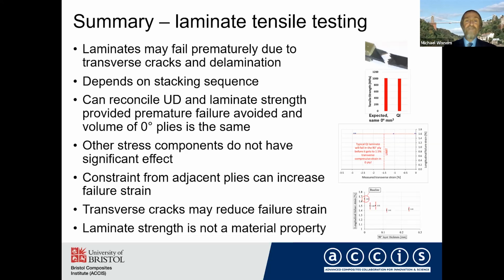stresses transverse to the fibers don't have such a large effect. We've also seen that constraint from adjacent plies can increase the failure strain, and that transverse cracks may reduce the failure strain. But I think the big message from this is laminate strength is not a material property, because it depends on many other factors.